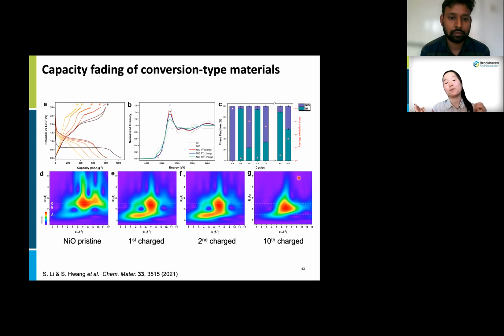Multimodal analysis is also powerful to address the problems batteries have. These graphs represent the discharge and charge profiles of nickel oxide, one of the conversion-type materials, and the x-axis represents the capacity. As cycles proceed, the capacity is degrading. And to figure out what happened in nickel oxide, we got nickel K-edge X-ray absorption spectroscopy, and we found that the conversion reaction is not fully reversible, indicating that lithium is not extracted fully.